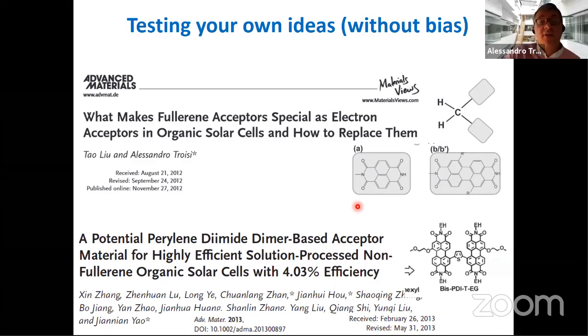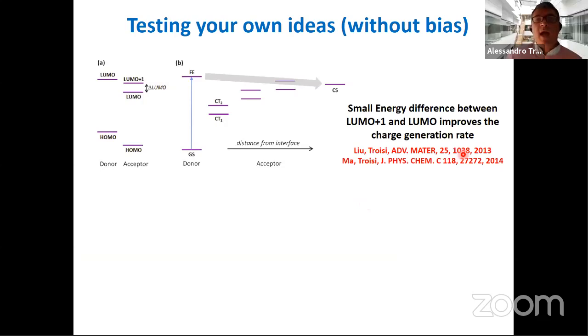and check if one particular idea was valid or not. So in this particular case, our idea was that an electron acceptor for organic photovoltaics is good if the energy separation between LUMO and LUMO plus 1, the computed LUMO and LUMO plus 1, is small. So the idea was that when we put this characteristic in the model Hamiltonian, the charge generation is much more efficient, while if the gap is slightly too large, there is some sort of anti-tunneling effect, so that depresses the rate of charge separation. It doesn't matter if the model is right or wrong.